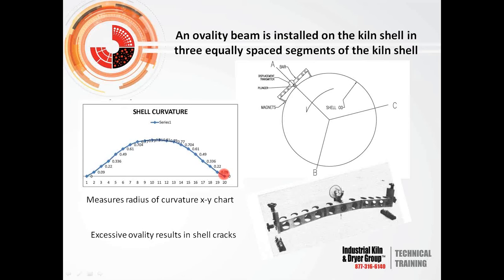As that slope of that line starts on the left-hand side coming up, when that line's straight, that's telling you there's very little difference in slope, which basically means the tire's supporting the shell well. And then when you get to the top, you can see a flat line up there. It didn't die, but it's flatlining. Essentially that's telling you the gap has created a relatively large flat spot, which is this flexing we're talking about, the results.